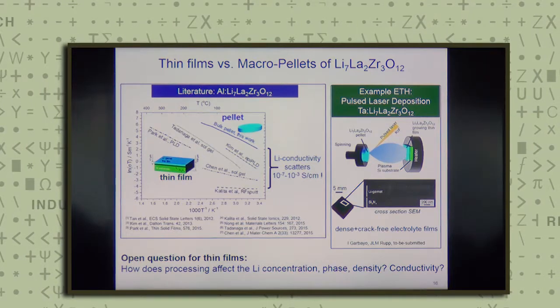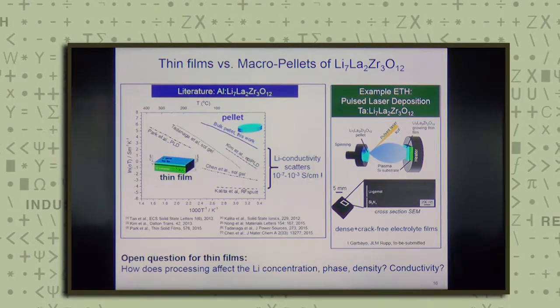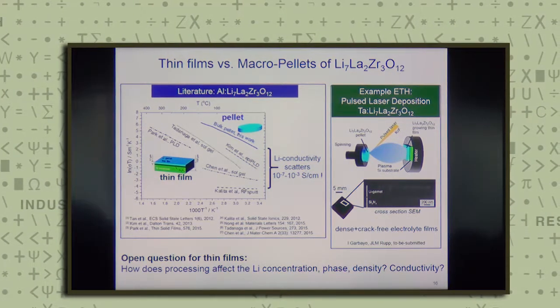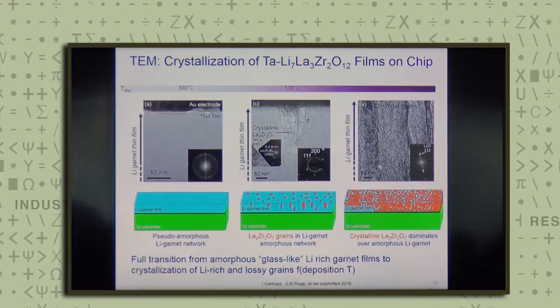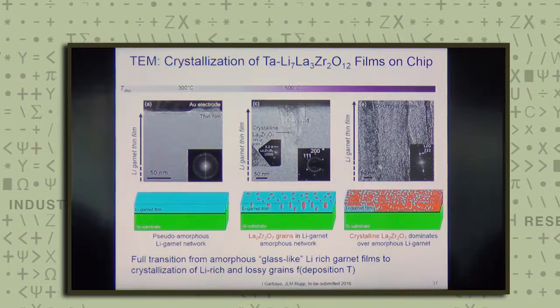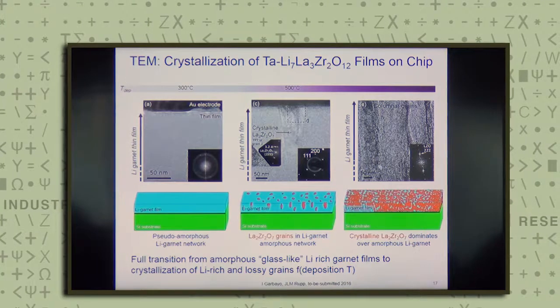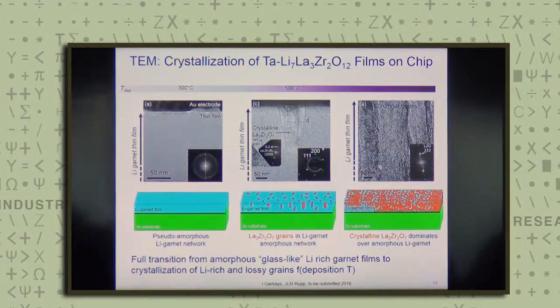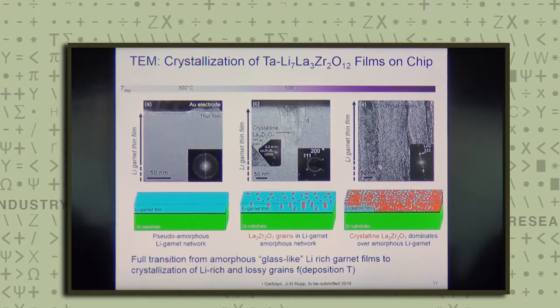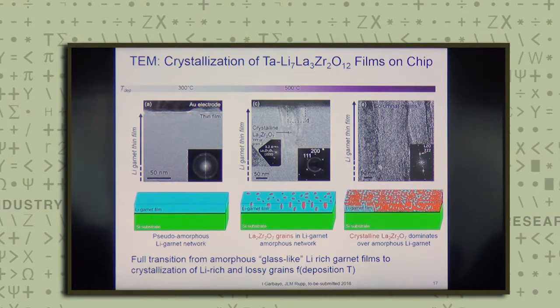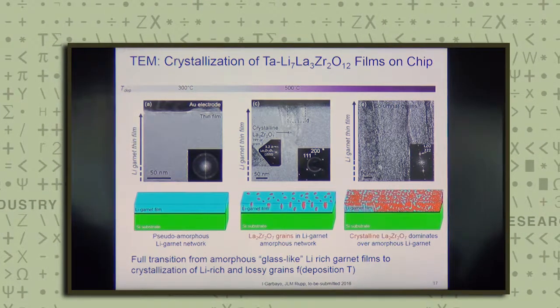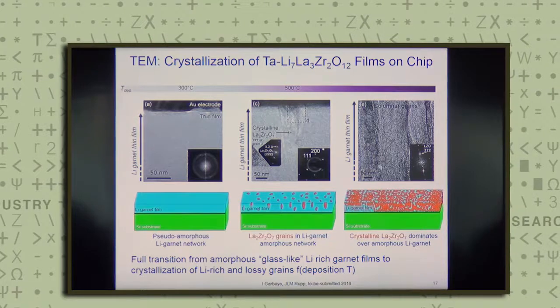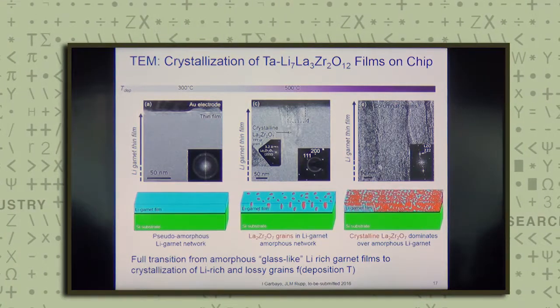Therefore, we have done a model experiment where we composed microbattery lithium garnet thin-film structures, and we investigated how the processing temperature can affect the conduction. The take-home message from this slide is pretty simple. You can choose different thin-film processing temperatures, for instance, in a pulsed laser deposition system. And if you go to very low temperatures, you come to a very amorphous, glassy type lithium garnet structure.